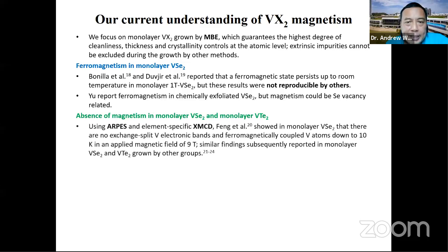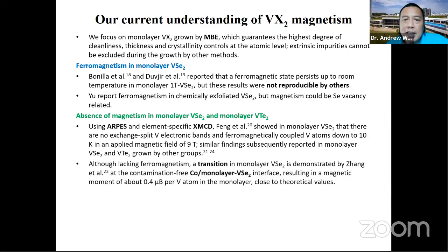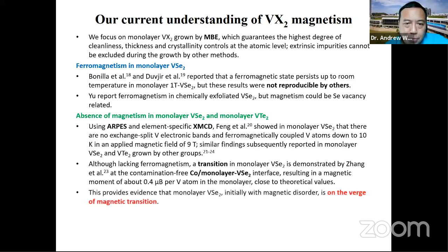And the fact that many people, including us and the Batzill group, also didn't show magnetism in vanadium diselenide also suggests that this material is intrinsically not ferromagnetic. But although it is not ferromagnetic, we showed that by depositing a ferromagnetic metal like cobalt, we could induce interface hybridization and make it magnetic.